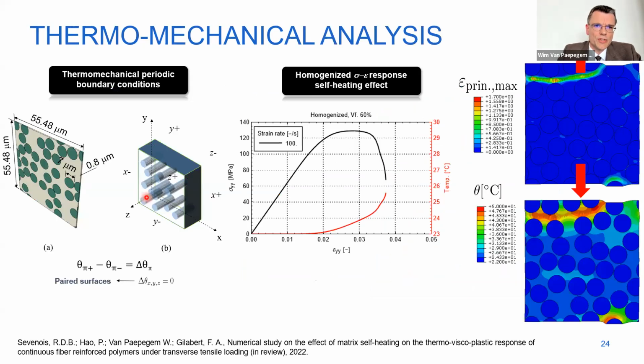And the last thing to mention is thermomechanical analysis. This is something we are doing recently, not only applying periodicity in mechanical loads, but also including temperature. In this way, we can start to look at other effects like self-heating. So this is the stress strain curve in transverse tension at a strain rate of 100 per second. So this is extremely fast, more like for impact and crash simulations. This is the homogenized stress strain curve, and this is the temperature.